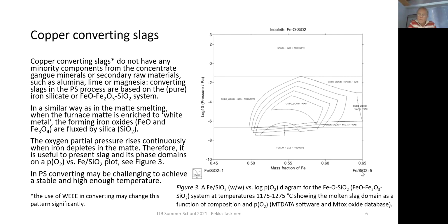And often in converting step, we are using phase diagrams like this. This is a special type of projection of the normal phase diagram Imam showed you and I showed you on Monday on iron silicate slags, but it is a composite of several isotherms as a function of the mass fraction of iron, and then this ordinate axis is the prevailing oxygen partial pressure of the system. So we are moving in converting from the low or lower oxygen partial pressure of the furnace matte